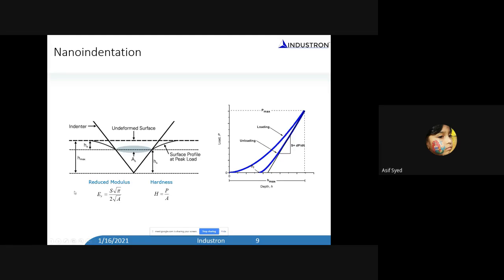Once you know the stiffness, in this equation you can calculate the modulus. For example, if you have a material for which you know the modulus by some other technique, X-ray or sound or something, like fused quartz, then I can do an indent experiment and measure the stiffness of the contact at a given load. For a given penetration depth, I know the geometry, and from the geometry I can approximately calculate the contact size. In our case, I know the force I applied, I know the stiffness, and I know the modulus, so I can compute the contact size, which is basically the area that I've shown here in a shaded color for a given depth. In that way, we can calibrate the tip for a given depth. What is the calculated area?